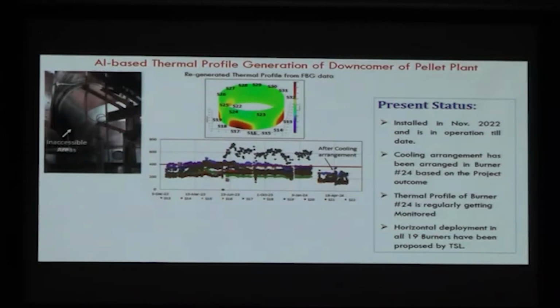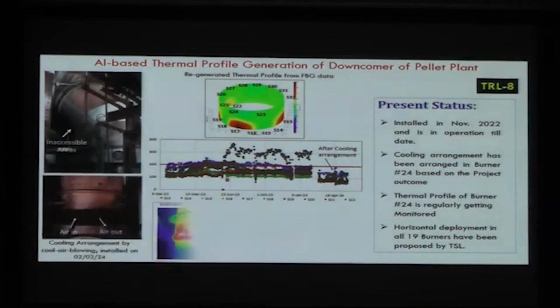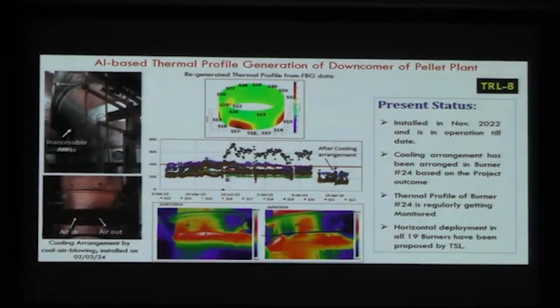What we have observed, look, this is the backside, sensor number 21, and temperature was continuously increasing, has gone up to 700. That means it was continuously giving an alarm which was not detected by thermography, but when this data showed it, a precaution was taken. Immediately a cool airflow arrangement was made. This is July 23, and this is March 24, when they did the cooling arrangement. The cooling arrangement was done on the 2nd of March. So the temperature dropped. That means it has helped that burner, because it was an instrumented burner and the whole thermal image was ported to their control room. They could do this preventive measure, and that's why the temperature dropped and the failure could be prevented.